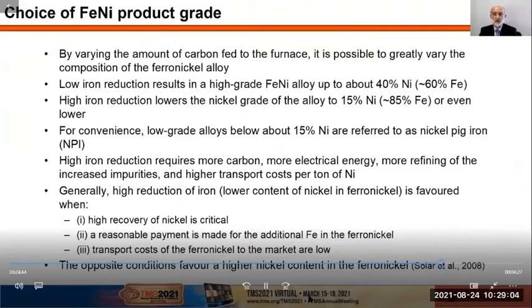And it's possible, by varying the amount of carbon fed to the same furnace, to greatly vary the composition of the ferronickel alloy, all the way from the nickel pig irons with very low nickel, all the way up to a high-grade ferronickel alloy, up to about 40% nickel, say 60% iron. High iron reduction requires more carbon, more electrical energy, more refining of the increased impurities that result, and higher transport costs per ton of nickel.